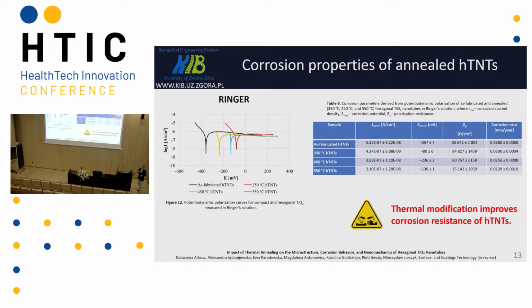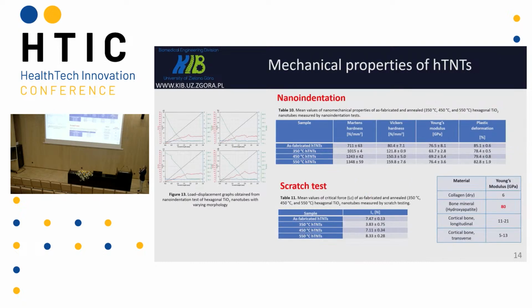How does it influence corrosion resistance? Thermal modification improved the corrosion resistance, so it is also in the range dedicated to, or required for, implant material. What about mechanical properties? They depend on thermal modifications, so generally on the anatase content in our sample.